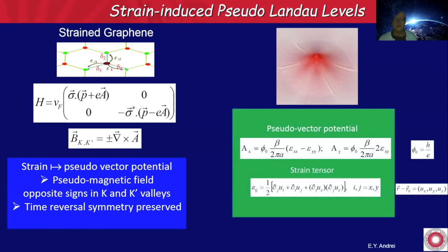And this is just for the expert, the pseudo vector potential is a direct function of the strain tensor in the system. So what you will get is, let's say, a pseudomagnetic field pointing up at the apex of this blister, and the pseudomagnetic field pointing down around it, because you must have a zero net magnetic flux in the system. So here we have a recipe of creating flat bands that look like Landau levels, but they are created by strain rather than an external magnetic field.